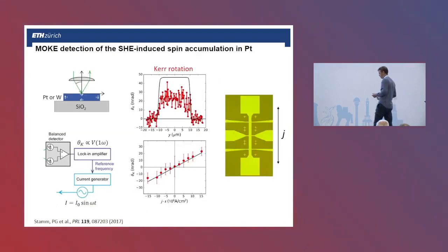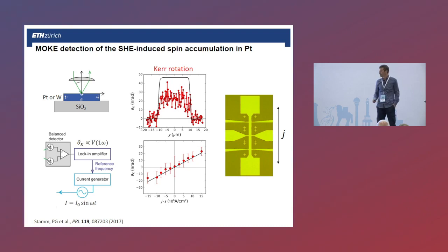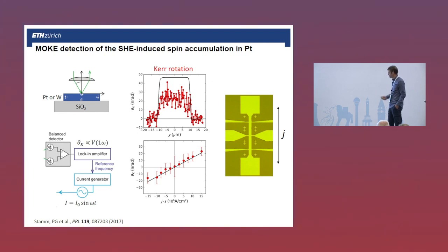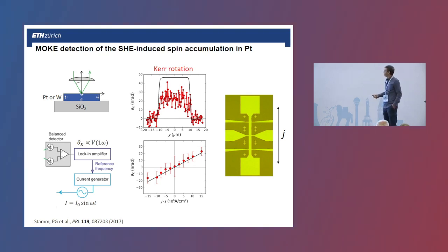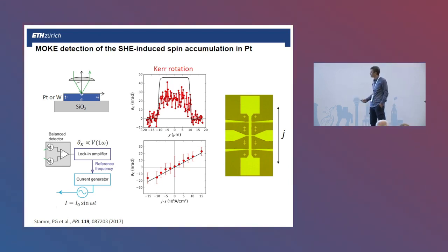These effects can be detected directly. In an experiment using a platinum Hall bar of 5 to 200 nanometers thickness, we used a scanning magneto-optical Kerr effect microscope, focused a laser beam onto the surface, scanned it across while injecting an AC current. We measured the Kerr rotation during current injection and observed a non-zero signal — a longitudinal MOKE indicating spin accumulation in the plane of the sample. This signal scales with the amplitude of the current, as expected.